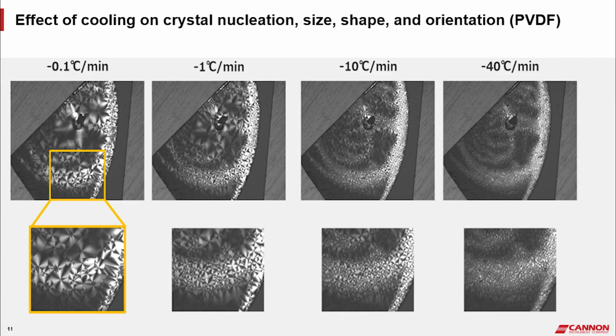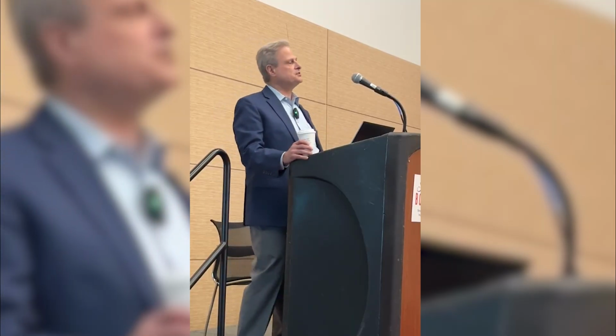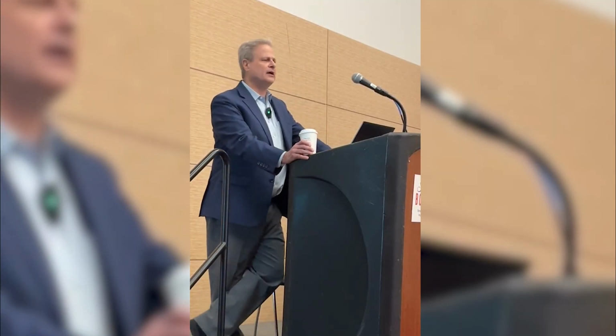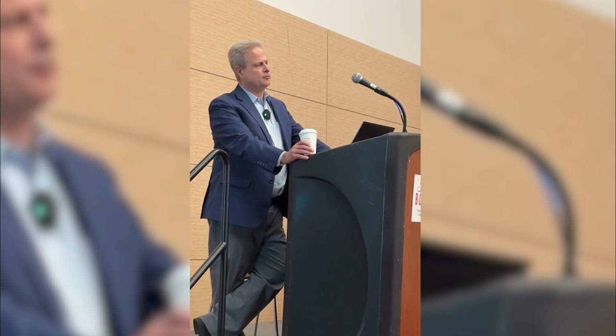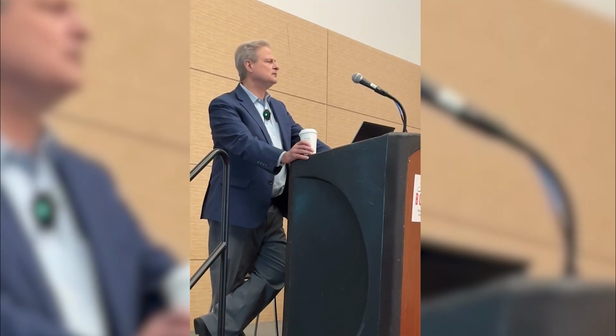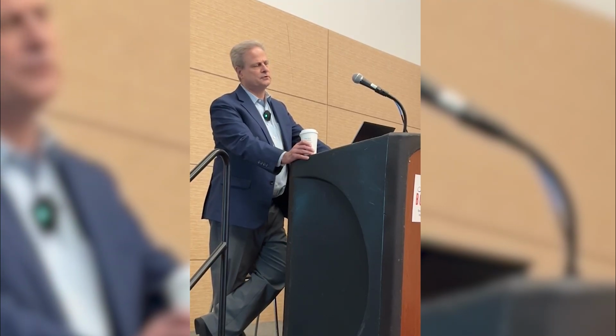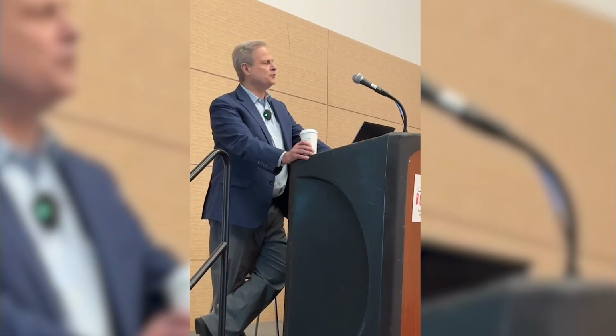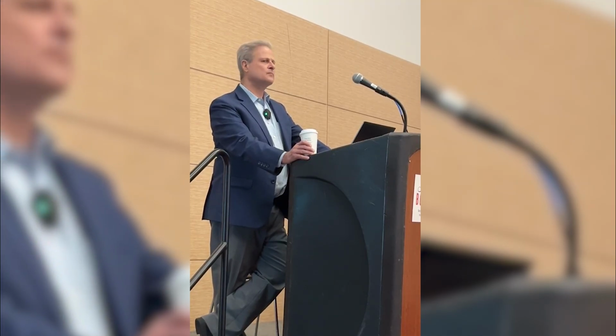And as we go to slower and slower cooling rates, we get less nucleation, but really nice large crystals. Now, again, I think this is profound. There's all different types of crystal structures. This camera is sensitive enough to look at things like spherulites and more fibrous type crystals. When you get into lamella type crystals, if they fold enough on each other, we could see it.